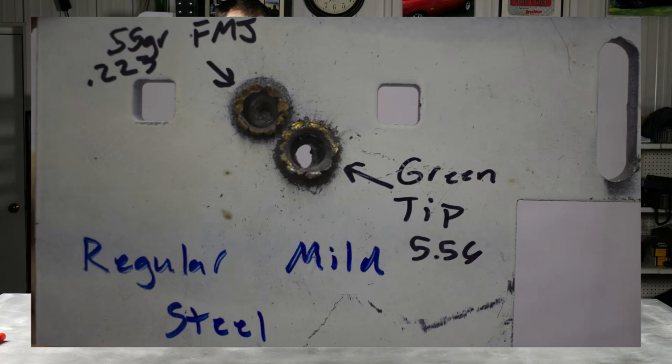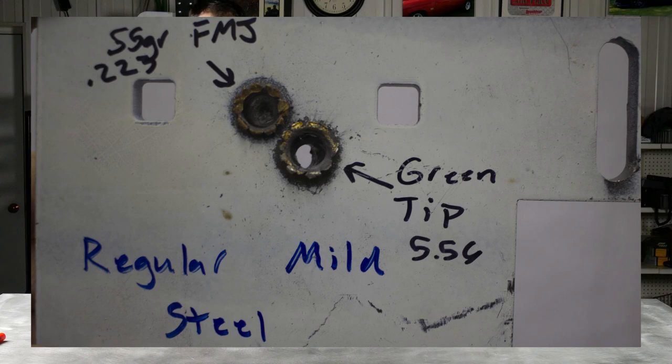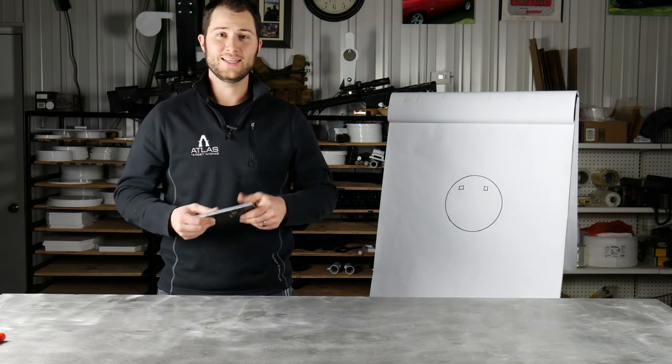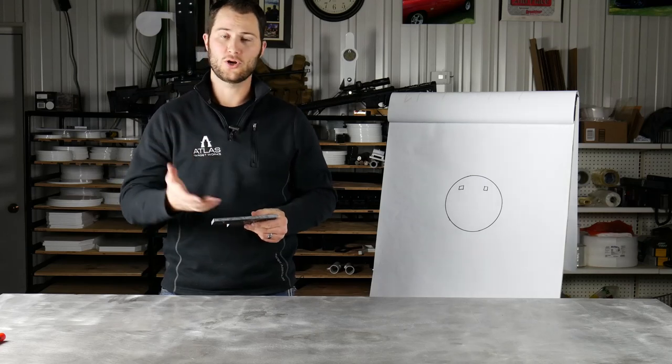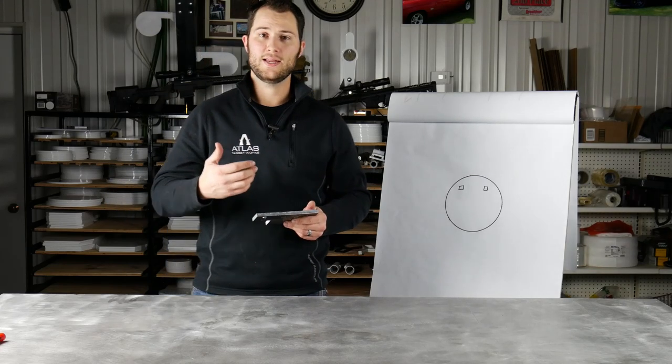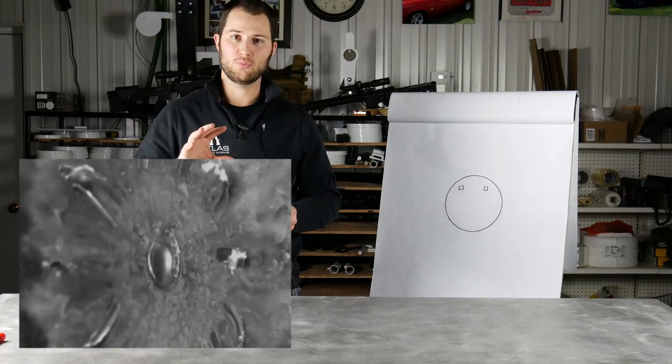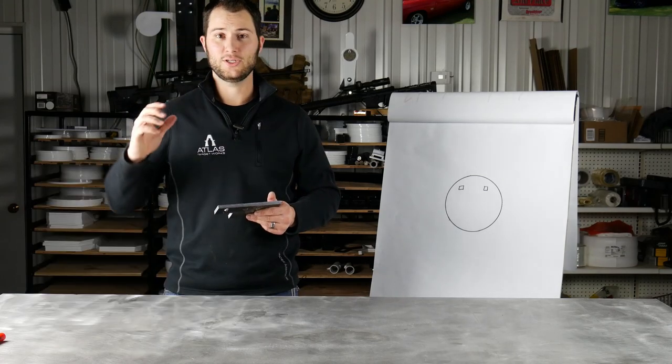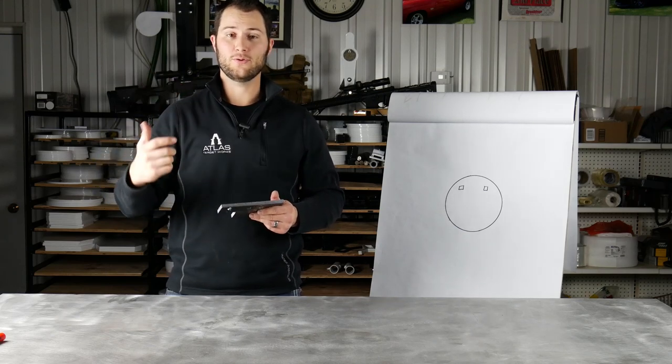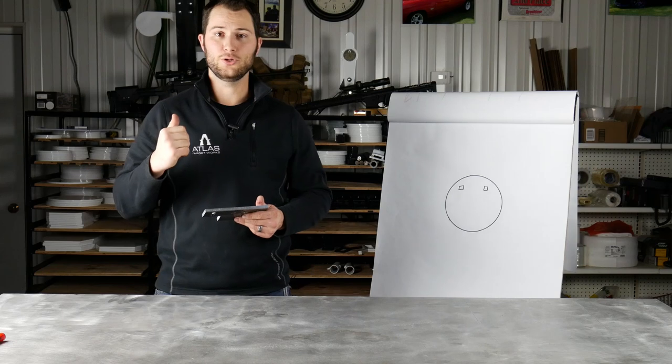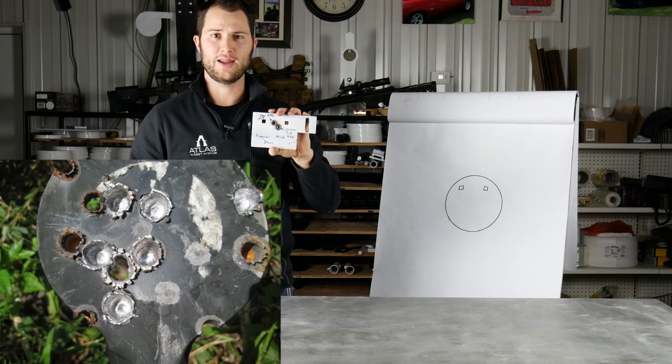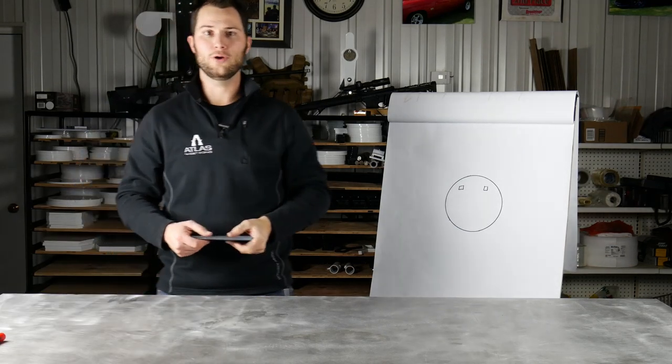Here's an example I have of a piece of 3/8 mild steel that I shot at with green tip 5.56 and then 55 grain full metal jacket 223. The 5.56 went all the way through and the full metal jacket went most of the way through, actually bulged out on the backside of the target. This can actually be more dangerous, that bottom of that pocket is curved and it doesn't dissipate all the energy by fragmenting the bullet on the surface like it will on AR500 steel. It actually goes in and it can send a huge portion of that bullet if not the whole thing back with enough energy to come back at the shooter. Not only that, but those individual spots, you couldn't shoot that hardly any at all even with just a 223 and have any bit of a target left when you're done with one outing.